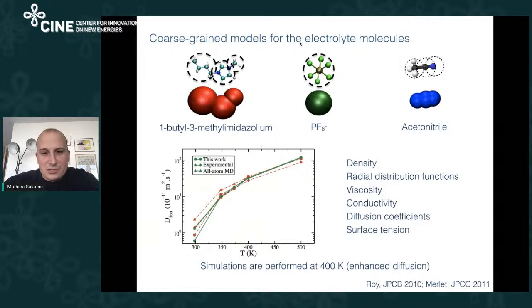A problem is that these simulations were very costly at that time. Now we do better, but at that time our code was not very efficient. So we decided to simplify the liquid a bit, and to do this, we use what we call coarse-grained models. So you have here an example of an ionic liquid, butyl methylimidazolium hexafluorophosphate. And in order to have faster simulations, the cation is represented using only 3 sites, the red balls that you see here. The anion is represented by 1 site only, and for example, an acetonitrile molecule can also be a bit simplified, but not as much as the ions.